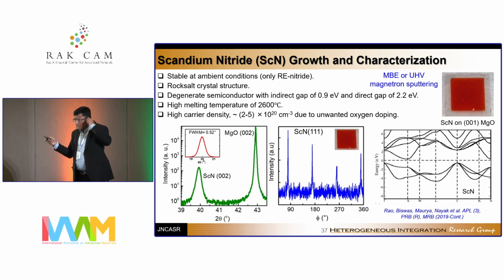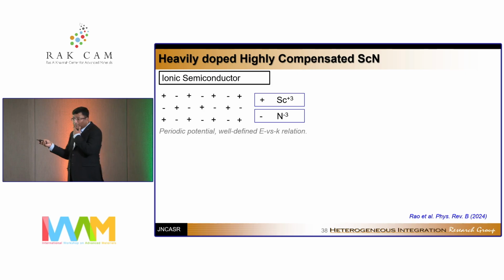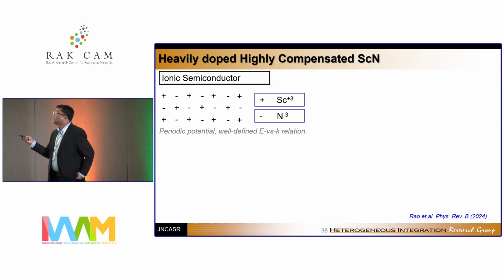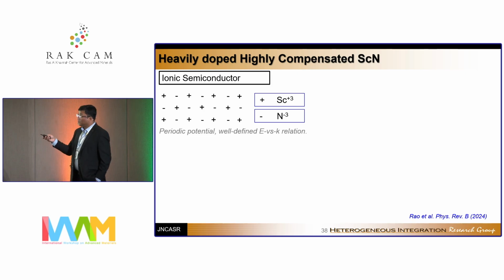And again, the strategy is very simple. You want to dope holes, right? So you can dope holes to reduce the carrier concentration. So if I take a normal semiconductor, let it be an ionic semiconductor, in this case scandium 3 plus, nitrogen 3 minus. These are periodic potentials, with a well-defined E versus K relation, energy versus momentum relation.